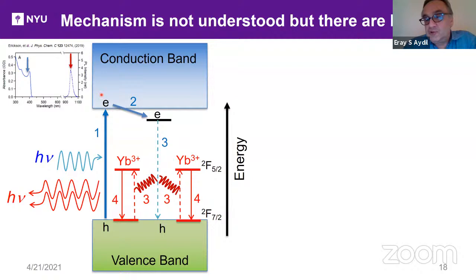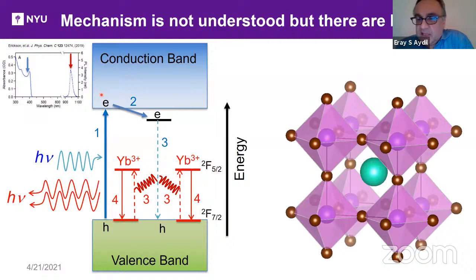How does that work? Well, people have proposed a defect that looks something like this. This is the unit cell of the cesium lead chloride with the cesium atom in the center in green and the lead with the chlorine forming the octahedra. And you have corner to corner sharing octahedra. So imagine now three lead vacancies. And then two of the lead vacancies get filled by ytterbium 3 plus ions. So you have a charge compensation. Three lead vacancies give you 6 plus, two ytterbium give you the 6 plus back, and the vacancy is left. So the idea is that perhaps this vacancy traps that exciton, and then two ytterbium are close by, and the exciton transfers energy to the two ytterbium. That's the hypothesis.